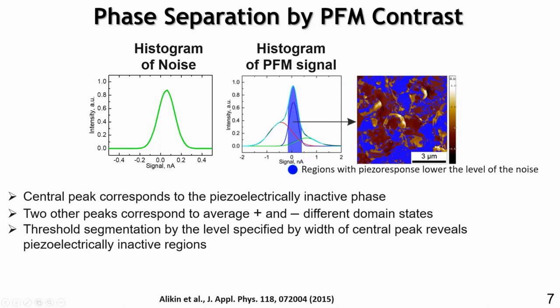And later, if we compare this percentage with a fraction of the phase from the X-ray, it was found that they're quite similar, despite the absolutely different basics of these techniques. This exact technique we implemented further to our BFO films.